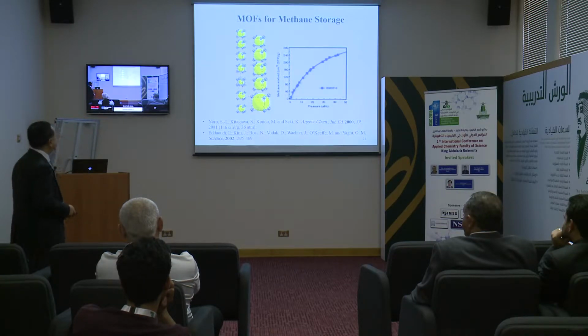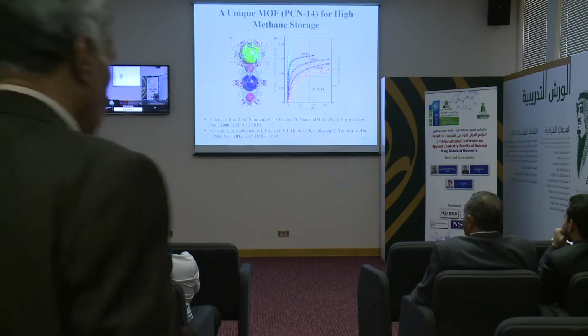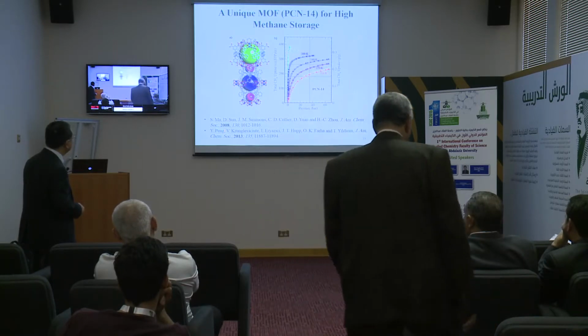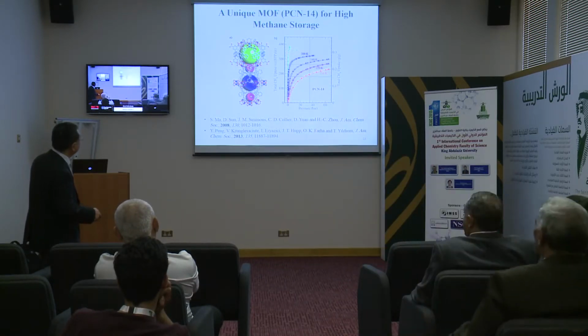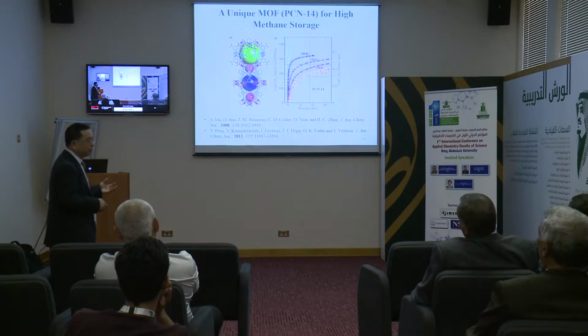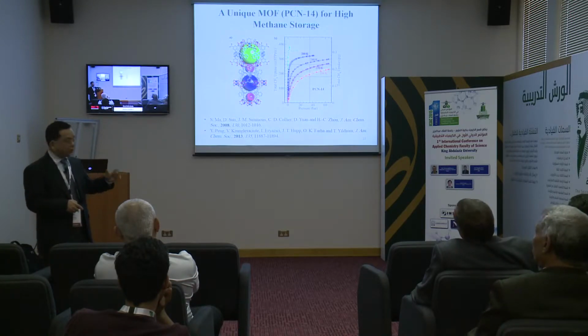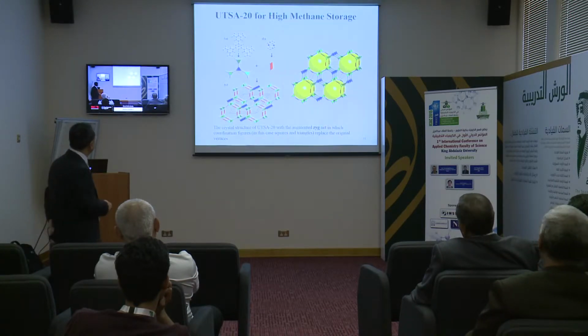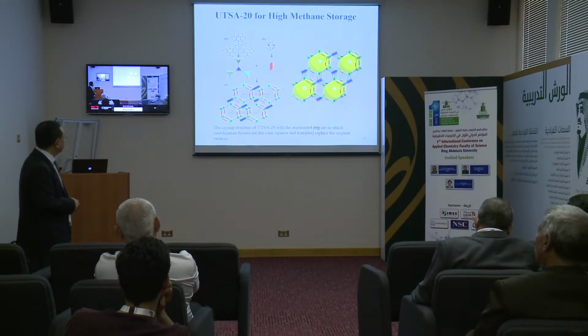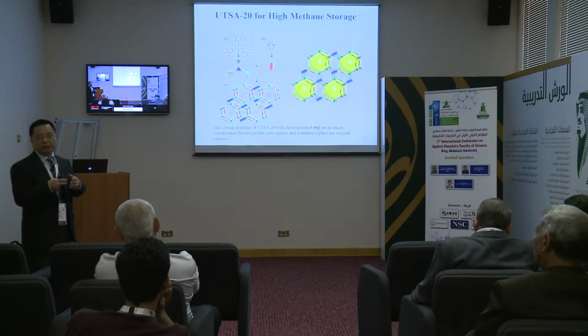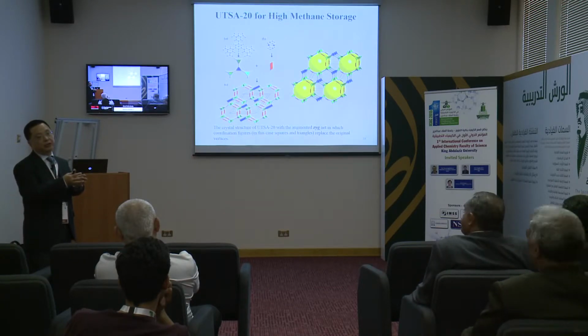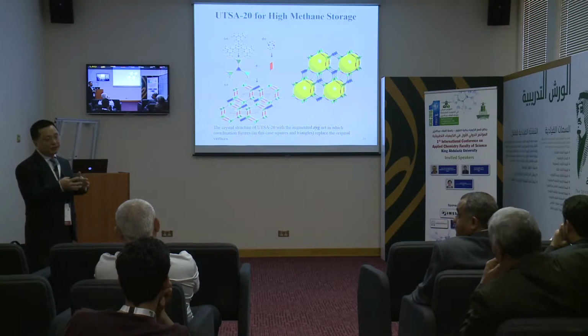So that's our focus. And Joe made an important contribution, and Omar also repeated the work, that basically this pore is specific, so kind of tuned. So we use a very simple and very small tetracarboxylate, and similarly with this paddle wheel, so the structure is kind of predictable. The uniqueness of this material is there is a high density of open metal sites, because the open metal site is the primary binding site of methane.